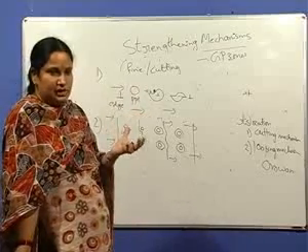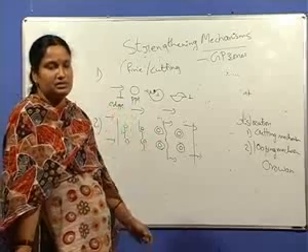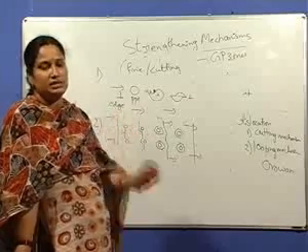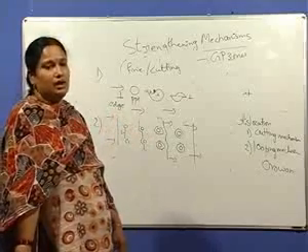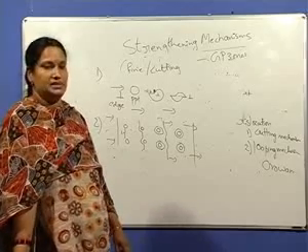If the precipitates are very fine in size, the cutting mechanism operates, and if they are coarser, the bending or bowing of the dislocation, that is Orowan looping, operates.